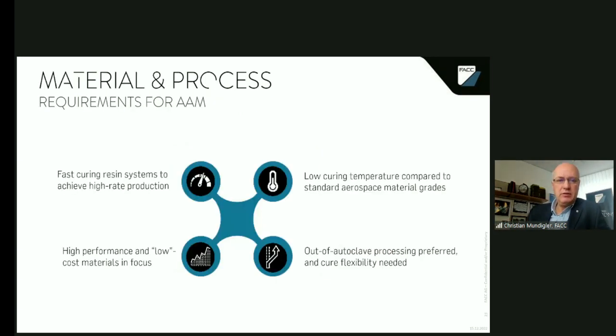And this means we need to look for fast curing resin systems to achieve a high rate production, high performance and low cost material in focus. Of course, if we tell that using an air taxi shall be at the same cost of a standard taxi, then we need to bring the cost down dramatically. So this is the motivation for us. Low curing temperatures compared to aerospace material and out of autoclave processes. And please think, if you use fast curing prepregs that cure in 10% of the original time, this means also that we save not only 90% of the time, but also 90% of the energy.